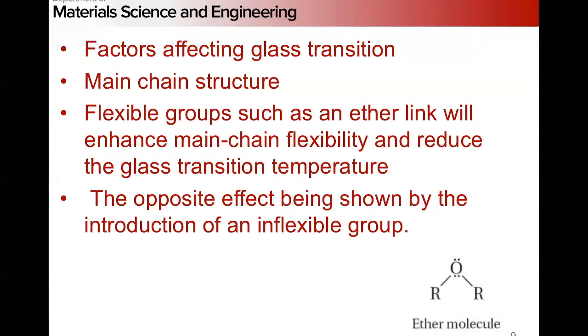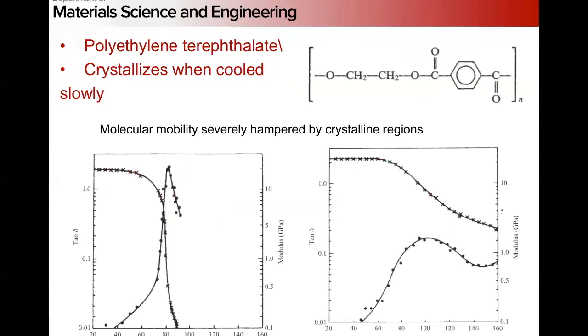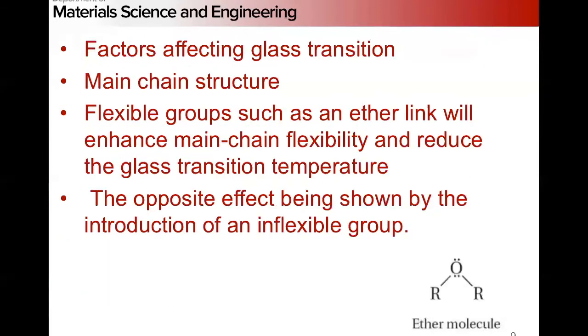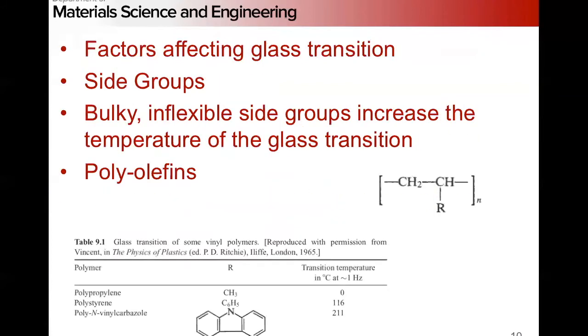Right. So you've got that oxygen with two side groups coming off here. This has a more significant degree of freedom than these terephthalate type structures, where you now have these big benzene type rings. This gives you a more rigid polymer chain, and is going to have a higher glass transition than a more flexible chain. Side groups also can have an effect on the glass transition. Bulky, inflexible side groups are going to tend to increase the temperature of the glass transition.